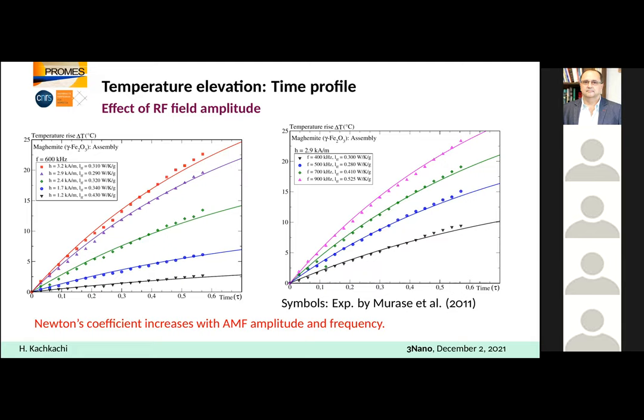When we have spherical nanoparticles embedded in liquid, there are several works that can compute this, or obtain some analytical formula for this coefficient. But for an assembly of magnetic nanoparticles, it's not so easy. It's really tough to develop a precise theory for this phenomenological parameter. That's why I'm insisting on this issue. We do need experiments that will help develop a more serious theory for heat diffusion within the assembly and out of the assembly. And of course, there is also the second stage that has just been ignored here. This question needs to be developed in the future.